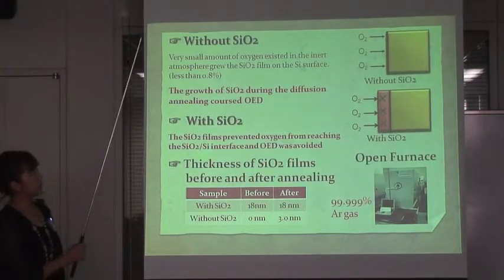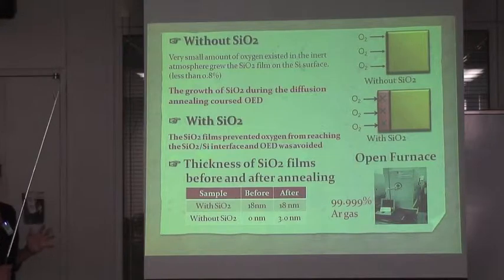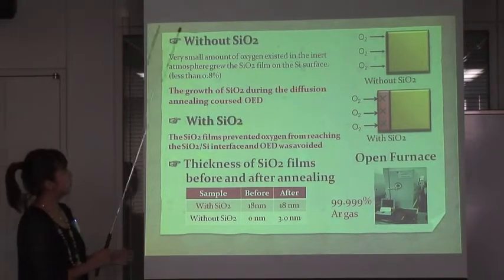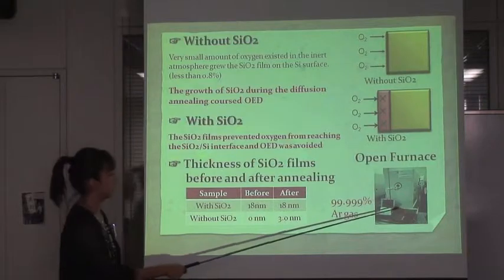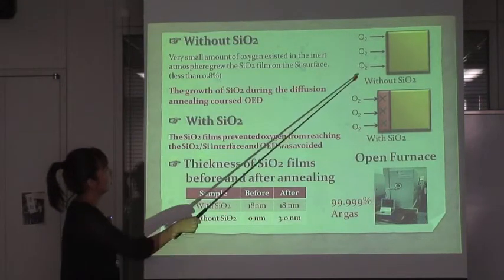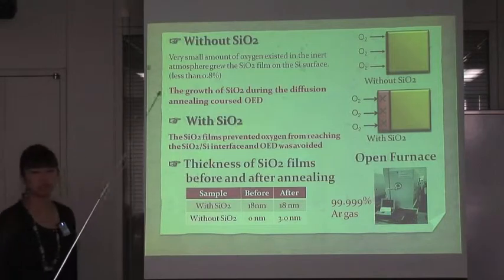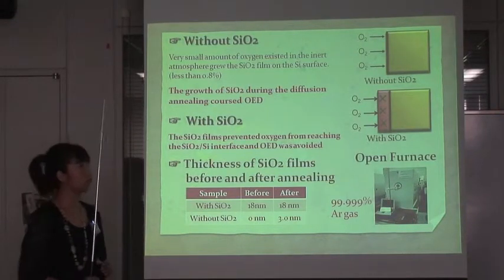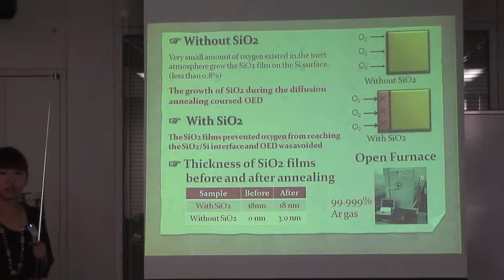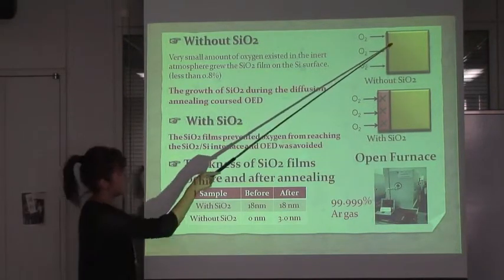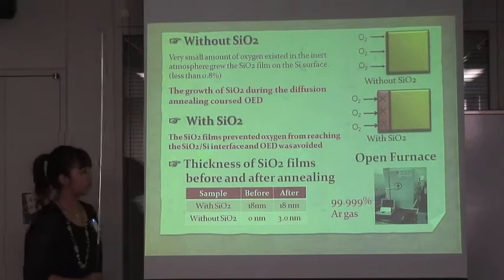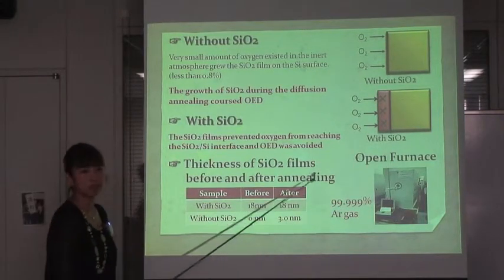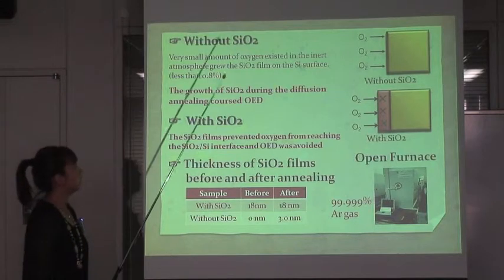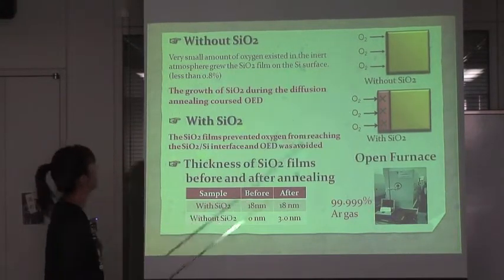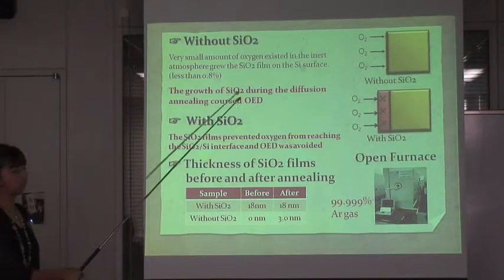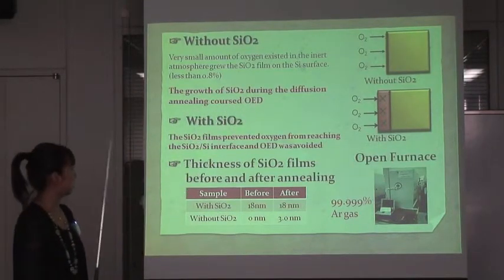In the case of samples without silicon dioxide, a very small amount of oxygen existing in the inert atmosphere grew silicon dioxide films on the silicon surface, in spite of our best effort to avoid leaking oxygen by flowing very pure argon gas. This oxidation caused oxidation enhanced diffusion, as I mentioned in the previous slide.